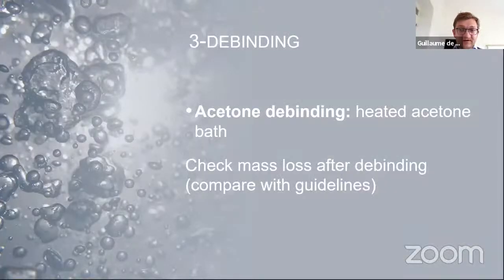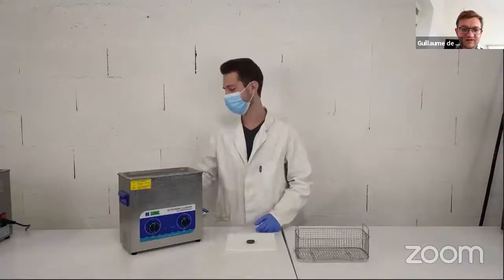So the debinding is done in heated acetone baths, and one of the really important things we say to our customers is the first thing is you need to respect the guidelines. In the guidelines, we give you times for debinding depending on the thickness of the part. And the second thing is you really need to check that you have the correct mass loss after debinding, which means you basically weigh the part before and after debinding. So here you can see how it's done.